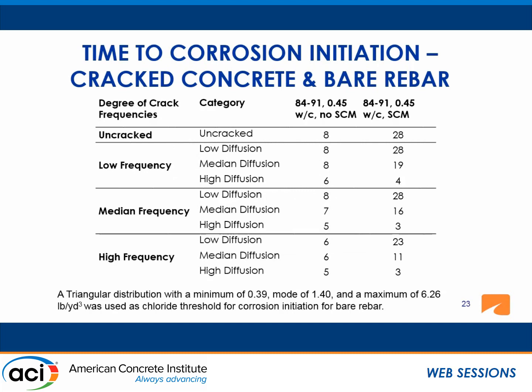These are the results from the service life modeling, and this is for the bare rebar. We did not use corrosion-resistant rebars yet. As you can see, from the uncracked situation, it gets worse as you go down. Even with low frequency of cracking, when you have high chloride diffusion through these cracks, you could have corrosion initiation within 6 years for the plain cement concrete. And at the absolute worst case scenario, at the bottom, with high frequency and high chloride diffusion, you have about 5 years.